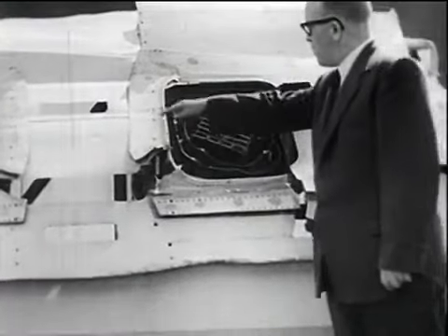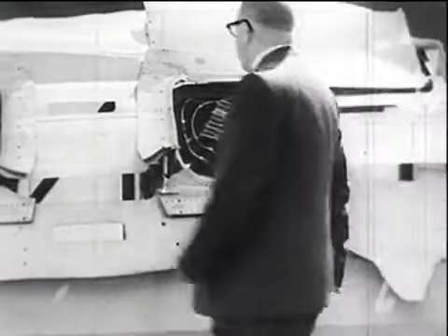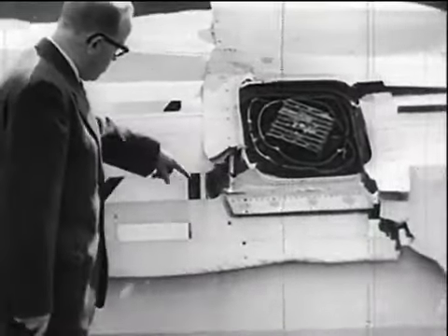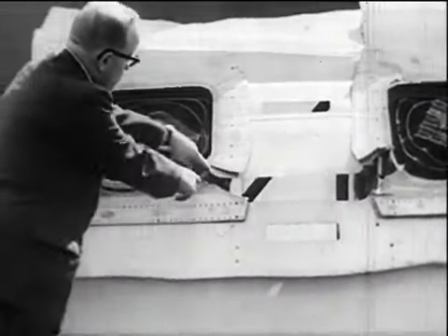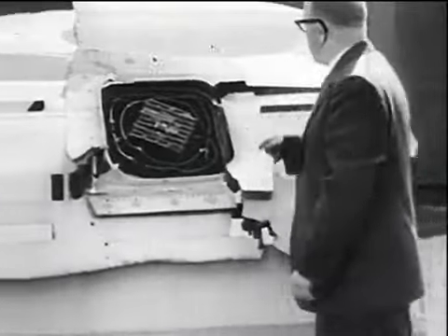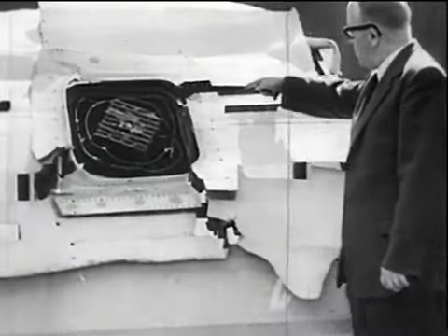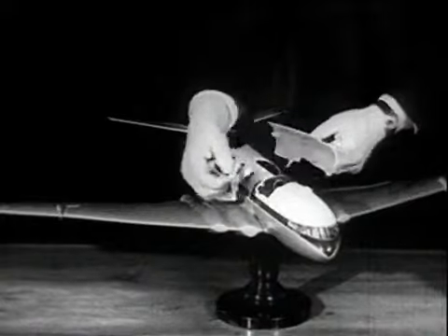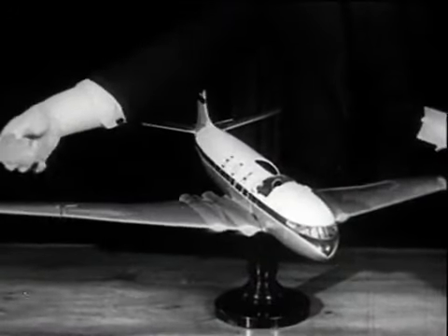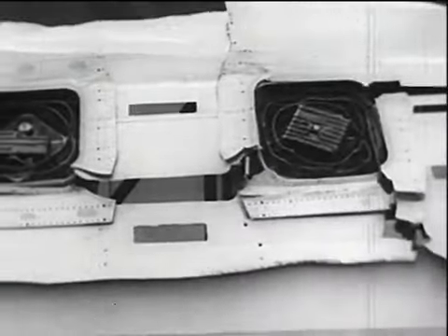On one side of the rear window, the failures run forward from a corner and pass through the front window. On the other side of the window, the failures run aft, so splitting the fuselage along the top centre line. Under the action of the internal pressure, the 2 halves opened outwards, broke away, and were projected violently along the wings. There is a strong similarity between the failures in the wreckage and in the fatigue tank.